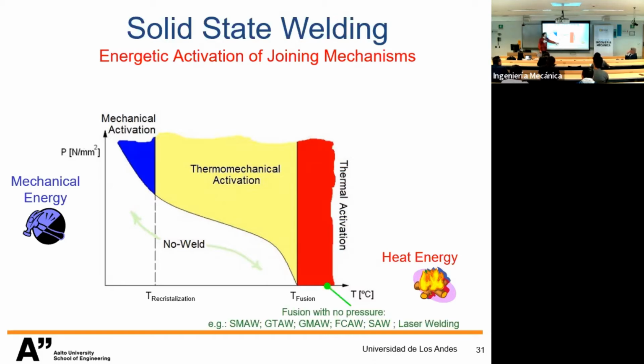So melting based, fusion based processes are in this line where we have in this graphic, sorry, we have temperature as a major effect of heat energy, although heat energy also produces expansion and residual stresses, and mechanical energy produces deformation, general pressure, but also generates dissipation by heat. But if we plot this pressure versus temperature as most important consequences that result from the application of heat energy and mechanical energy, we see that above the melting temperature with no mechanical energy, you have most of the fusion welding processes. And then you have a very important process that is based on fusion, but is insulated from the remaining world with the forging zone. And that is probably the most automatized welding process.